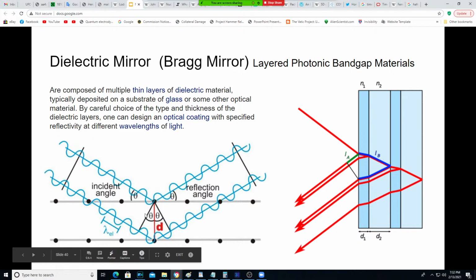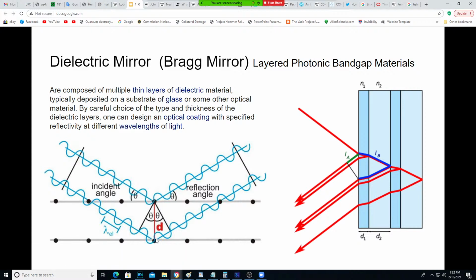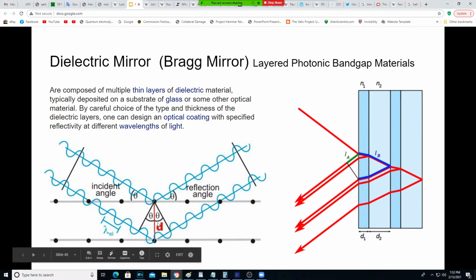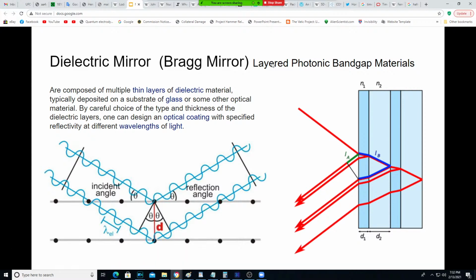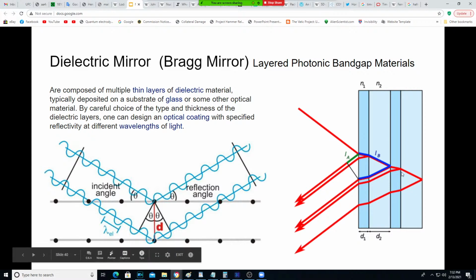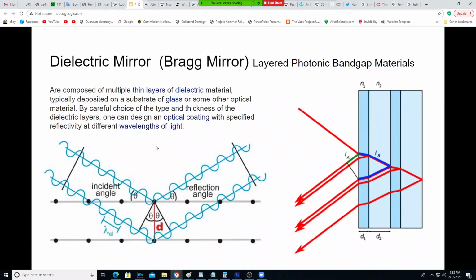And different frequencies go into the material and have different penetration depths, different interactions with every material. So certain frequencies will bounce right off the surface of the material, and some frequencies will penetrate deeper into the material and then bounce around, or sometimes they don't reflect back. But what a Bragg mirror, or a dielectric mirror, does is it tunes each one of these layers to those next frequencies, so that when they bounce off, all these frequencies sort of bounce back off. And it's very interesting what you can do.